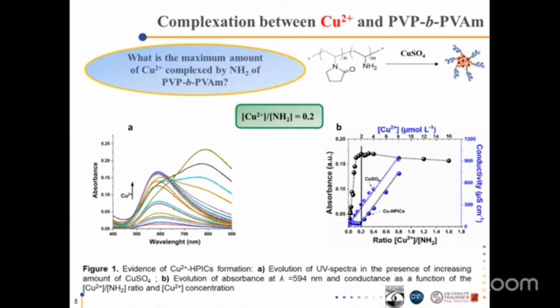Then absorbance was plotted as a function of the ratio between copper and amine groups to determine the stoichiometry of the complex formed. This is figure 1b, black line. A change in the slope was observed at ratio 0.2. This result was confirmed by the conductivity, figure 1b, blue lines. While the conductance of pure copper sulfate solution increased linearly with concentration, the conductivity of the polymer-containing solution remained constant up to ratio 0.2 and then increased with a slope comparable to that of the copper sulfate solution alone.